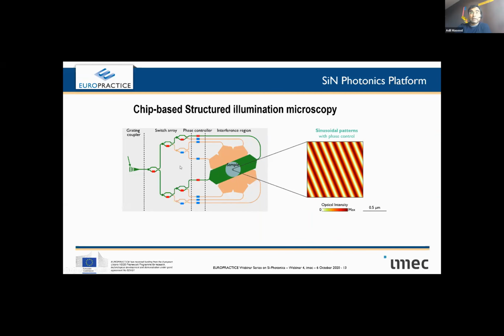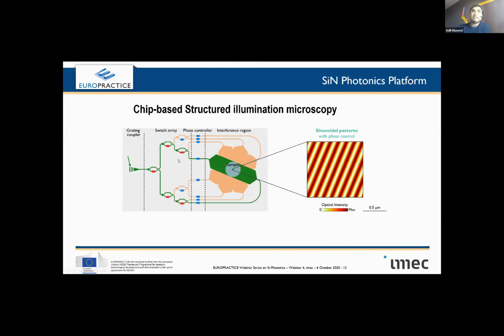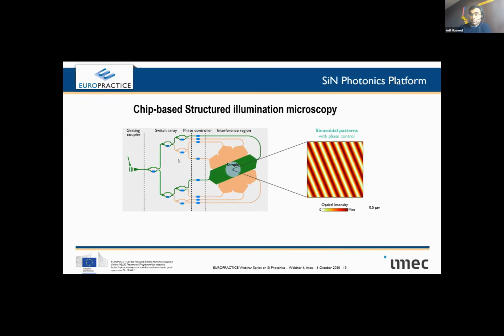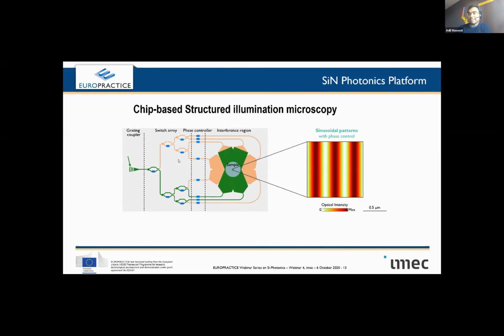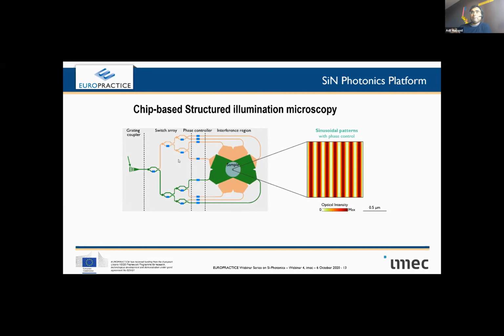Like in this animation, you can see that what is blinking red and blue are different thermal or thermo-optic heaters or thermo-optic devices, the heater layer, which I showed in the previous stack. And by controlling them, the light, which is all converging to the sample from different sides, their phases can be controlled. Hence, the sinusoidal pattern of interference on the sample can also be controlled and then selectively excite different fluorophores. And those images can further be used for fluorescence microscopy.